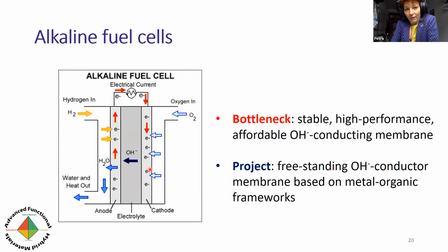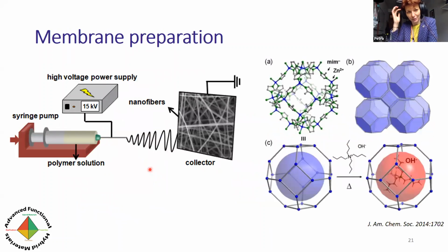There are a few hoops to overcome to make them stable under the conditions. Of course, we need to make them hydroxide ion conductors, and also to manufacture them and process them in a shape that lends itself to membrane applications. And of course, metal organic frameworks, being very highly crystalline, are typically very rigid. So in order to overcome the mechanical issues, what we did is we used electrospinning to process the metal organic frameworks in the form of a fiber mat.